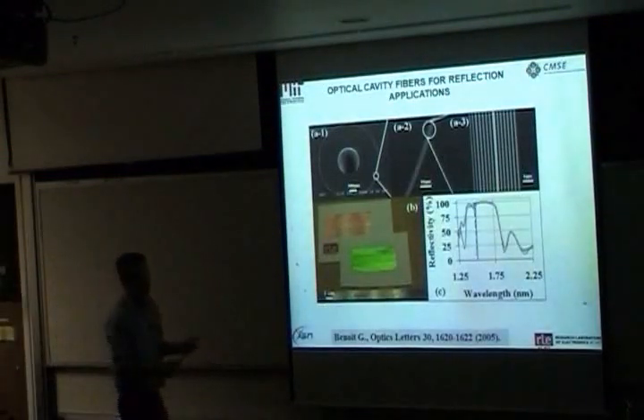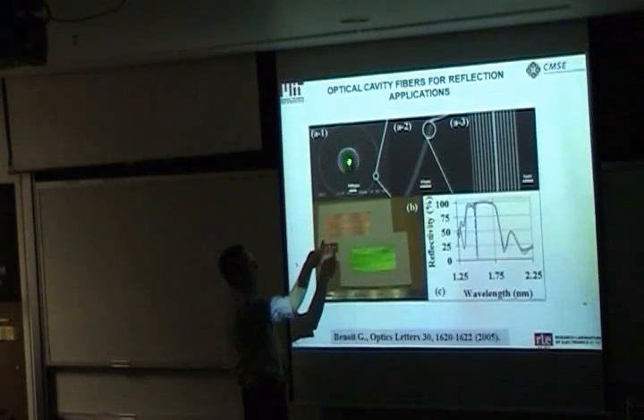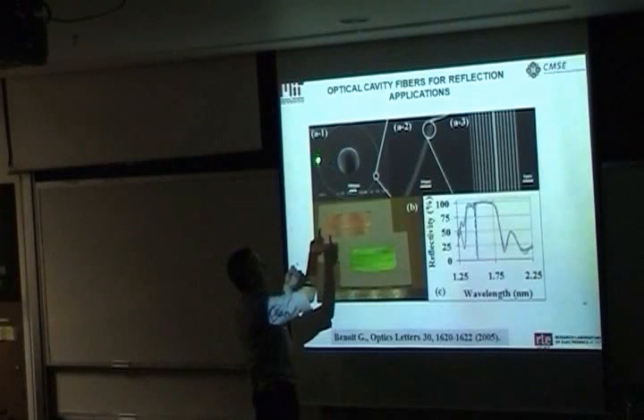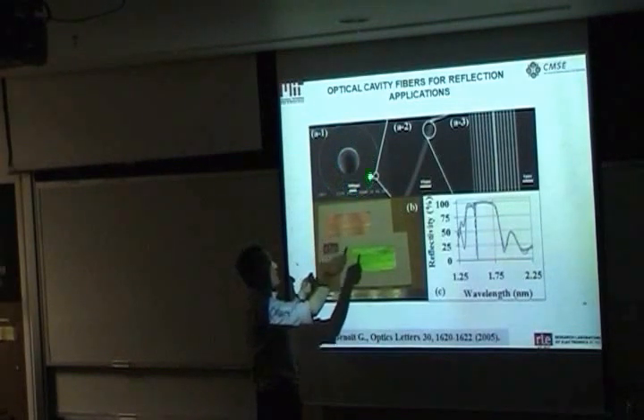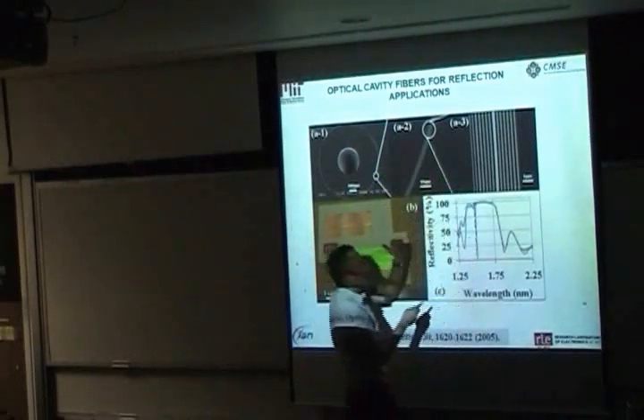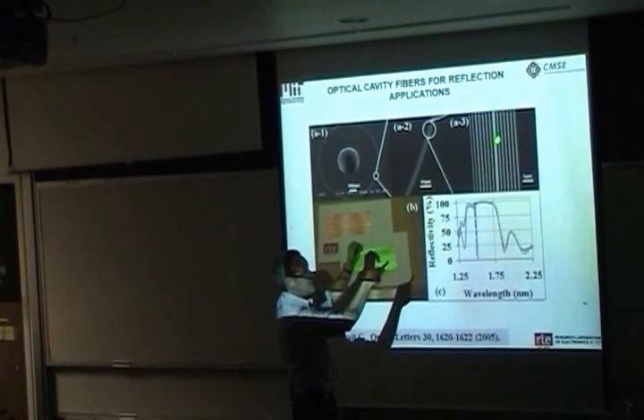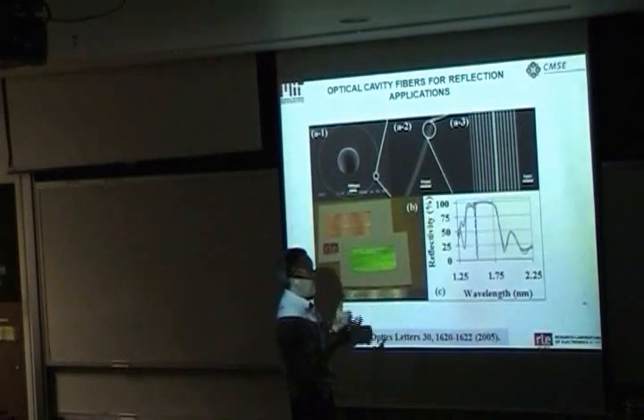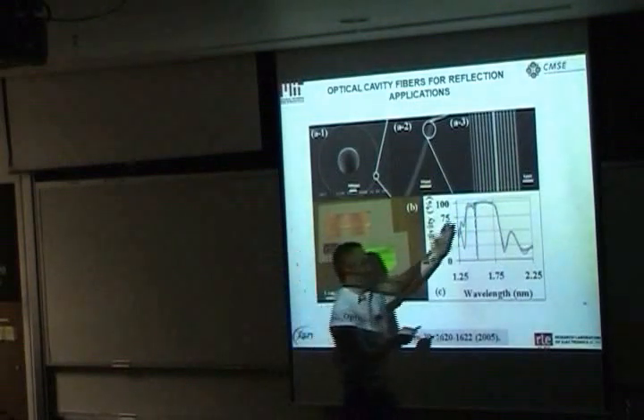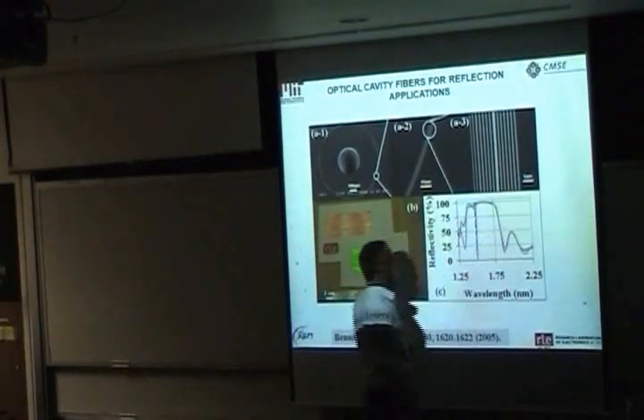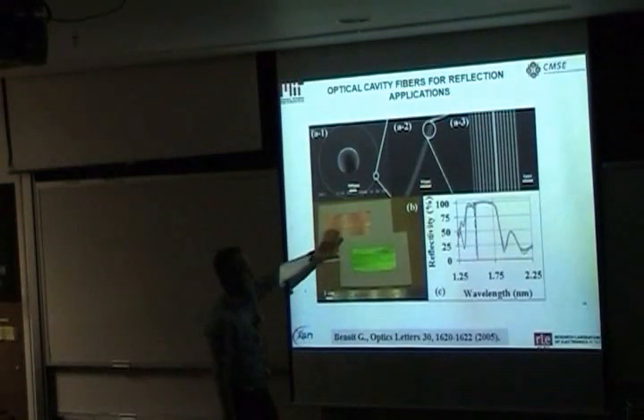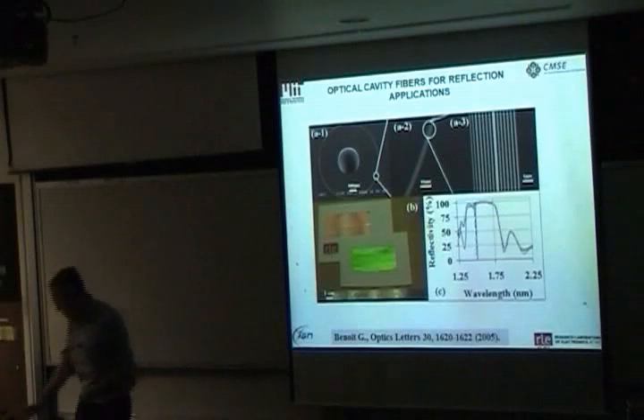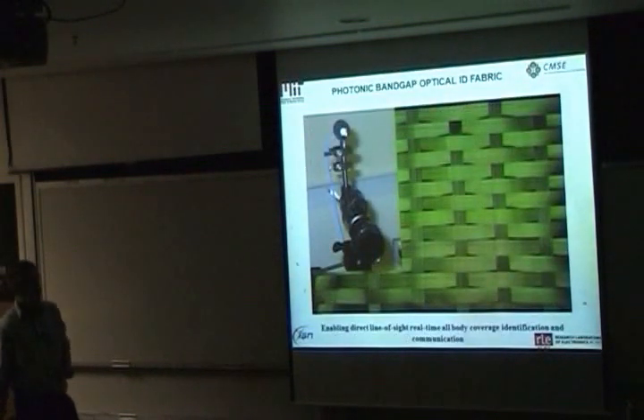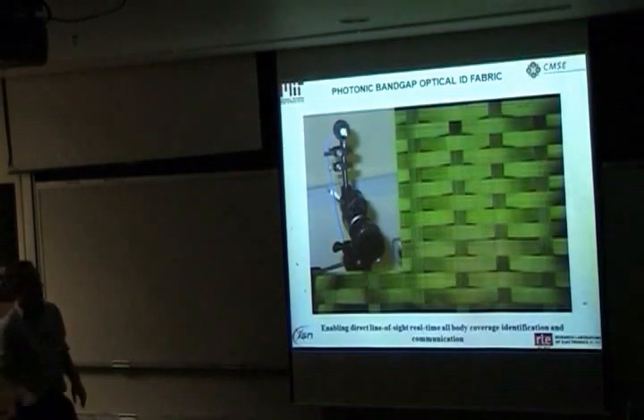So here's an example of fibers that now have a hollow core, but the hollow core doesn't serve any specific purpose. In fact, the entire photonic structure is now on the outer circumference. And again, we go through this process of increasing the magnification. And you can see there's a periodic structure, and then we insert a layer that is off the periodicity. And that layer actually gives you a very sharp transmission line in the otherwise broad reflection band. This is how these materials look. This is work that was published in Optics Letters. This work is being funded by the U.S. Army, and one of the ideas that we had there is actually using these to create fabrics that could be optically identified by just illuminating them with a laser.